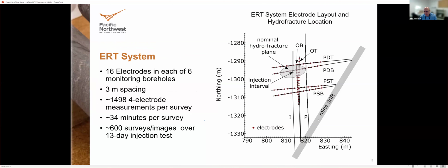So this is focusing on the ERT array. The electrodes in each of the monitoring wells are shown here in red dots. They were at 3 meter spacing in all of the wells, and they were designed to image this area in here. You can read some of the specs here. When you're in monitoring mode, these ERT systems run continuously. They'll collect a survey, which is a set of measurements, 1498 in this case, and that takes about 34 minutes. So your time resolution between images as the process is going on is about 34 minutes in this case. And these would run continuously as we were doing these fracture and flow experiments.